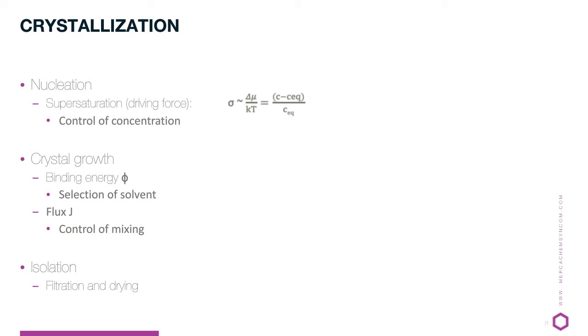supersaturation. Control of the concentration, as can be done by lowering the temperature, partly evaporating the solvent, or adding an anti-solvent, will result in a driving force for nucleation. For crystal growth, the binding energy, which is related to the interaction with the solvent used, as well as the flux, which is controlled by the mixing of the solvent solution, are the rate determining factors.